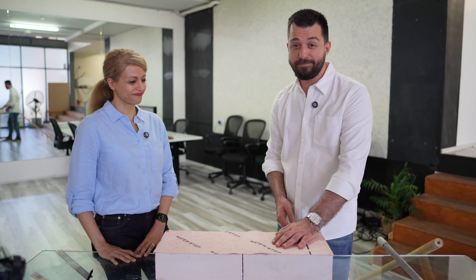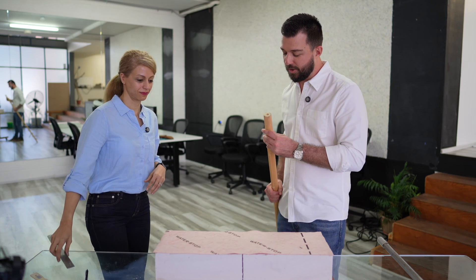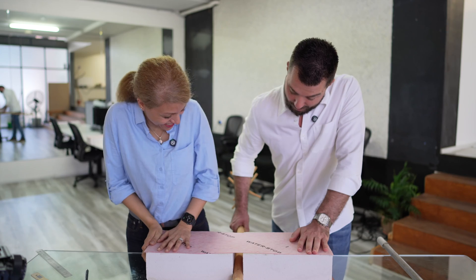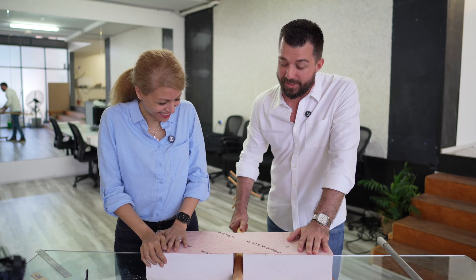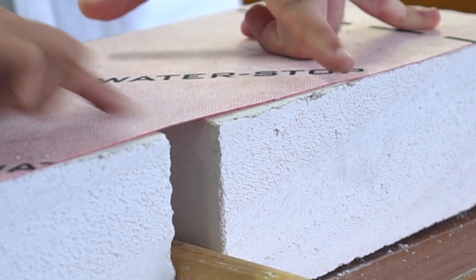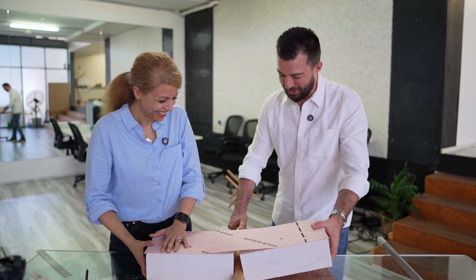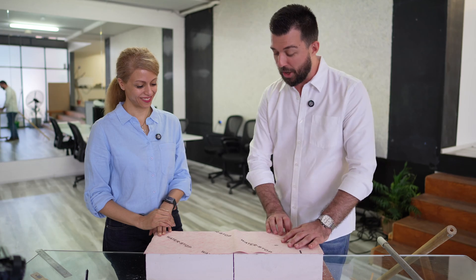Only one question remains — can we do any more? Oh yeah. We've got something — this one's around 32 mil. Let's try it. 32 millimeters of movement bridged. The structure has failed already. Yeah, the building's fallen down, but the membrane's still intact — so that is consumer confidence. You can see the membrane stretching a little bit here, where it becomes a little bit narrower, but still definitely holding together. It's actually very elastic — you can see the membrane is fully holding the structure together at this point. Back to zero and everything's still intact. I consider this a good outcome.